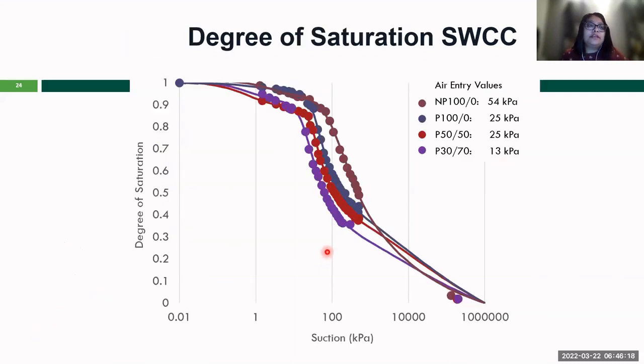And same thing for the degree of saturation data. If we just look into that, what we see for these polymer samples is that it behaves like the non-polymer samples at the beginning when there was no air entry. When it started to show the air entry, then it started to behave like the rest of the materials, like the sand materials. So these are the major findings from this data. And polymer amended samples require less energy, lower suction, to desaturate after the air entry value is reached. So that's another finding.